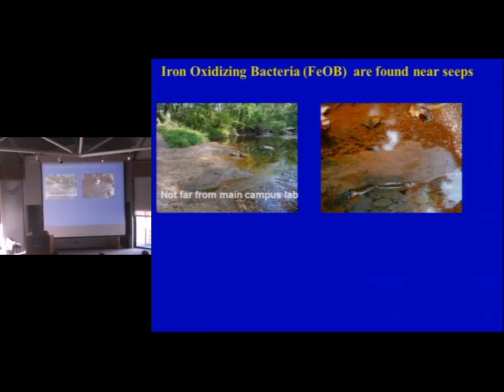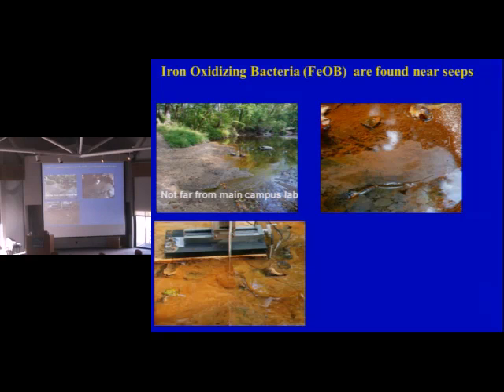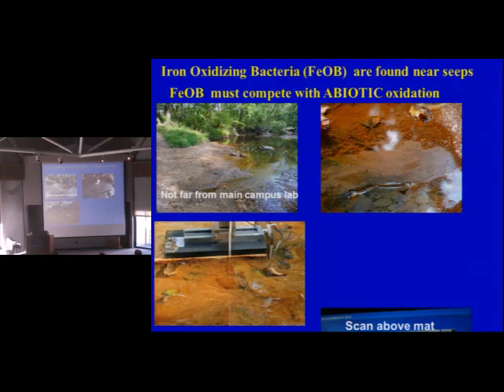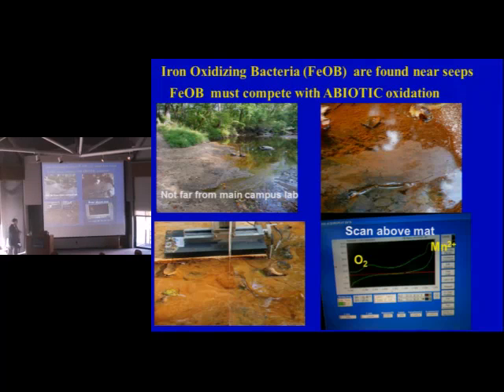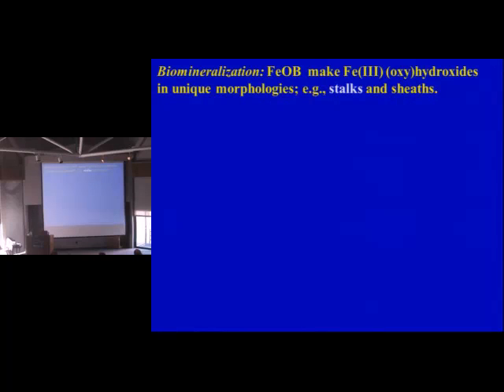This is not far from our main campus. You can see these areas where groundwater comes out. Sometimes you can see some orange and yellow colors. This you might be able to see a little bit better. There's one of our microelectrodes in. And this is actually what our scans look like on the monitor rather than replotted. So this is oxygen with some manganese in it. The iron's already been titrated out because it's in an area where we're not at low oxygen. Now we're going to talk a little bit about biomineralization first.